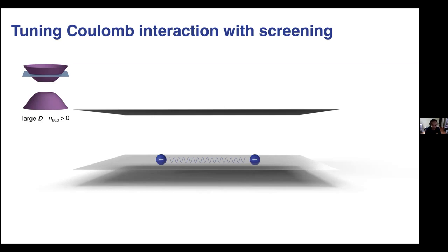In the ideal case, if you think of bilayer graphene as highly conductive and infinitely large, the solution to the boundary condition can be modeled by image charges, as shown here. That's 2 times the distance away from twisted bilayer graphene. Without the image charge, the two electrons experience an unscreened Coulomb interaction. And as you can see, when you add the image charge, the Coulomb repulsion becomes weaker because now you have the Coulomb attraction between the image charge and the electron. From this schematic, you can see that you really want this metallic layer to be very close to the twisted bilayer graphene, because that will increase the effect of Coulomb screening. So this hand-waving model shows the effect of screening from a nearby metallic layer. It reduces Coulomb correlation within twisted bilayer graphene.